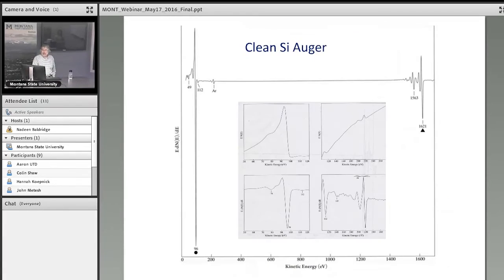So usually, Auger electrons look like this one here. This particular peak is the argon peak. This is a silicon Auger. Don't worry about the details, but it runs on a background like that. So you take a derivative of this background, and you get here one of the silicon Auger peaks, and another silicon Auger peak. They come in various pairs with many different signatures. So when you see one of them, you ask, what kind of Auger is it? You have to look at the other ones as well.